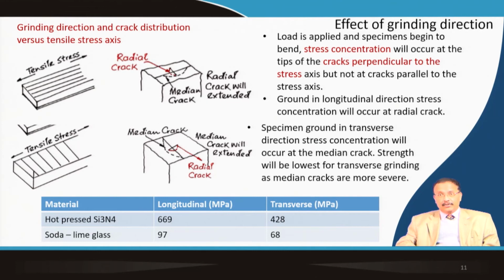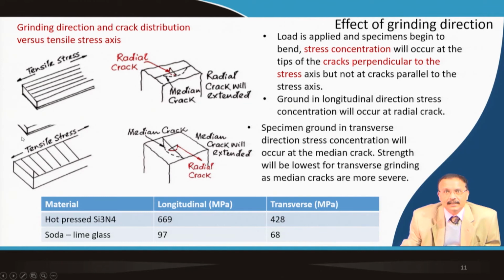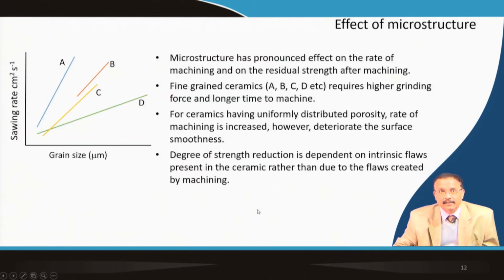Now, if the specimen is ground in the transverse direction, which is the second case, stress concentration will occur at the median crack. Here the median crack is this one. So, all the stress concentration will be along the median crack. The strength will be affected, and it will be lowest for the transverse grinding, as median cracks are more severe as compared to radial cracks. Experimentally, this is also verified in the case of hot pressed silicon nitride. Longitudinal, it is 669, the strength of the material after machining. In the transverse direction, if you do the machining, it is 428. The same thing applies for soda lime glass also. In the case of longitudinal, it is 97. In the case of transverse, it is 68. So, the direction affects the mechanical strength.